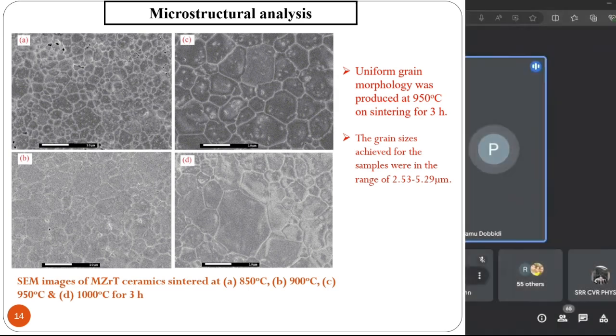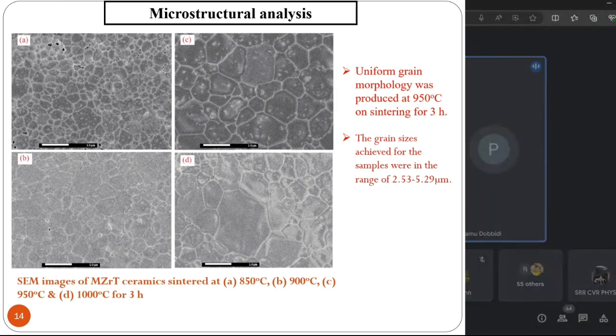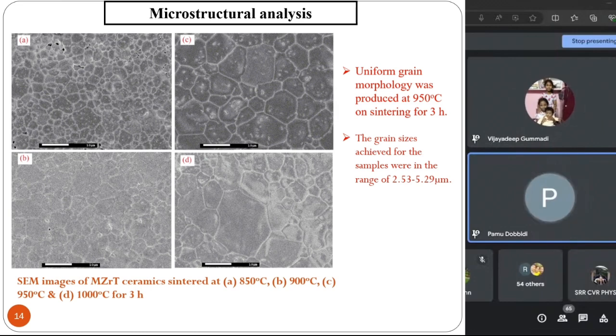well compacted material. Where is the density coming from, and what is the use of nanotechnology here? What we did is, we started with smaller particles, and when you fire them at 900 or 950 degrees C, you see that the compactness of the material is increasing. What is the reason? When you use nanoparticles, the surface to volume ratio is so high that the densification or sintering velocity is very high. This sintering velocity helps the material to get compacted nicely. That is the reason you have a very good microstructure that is possible at a low temperature.